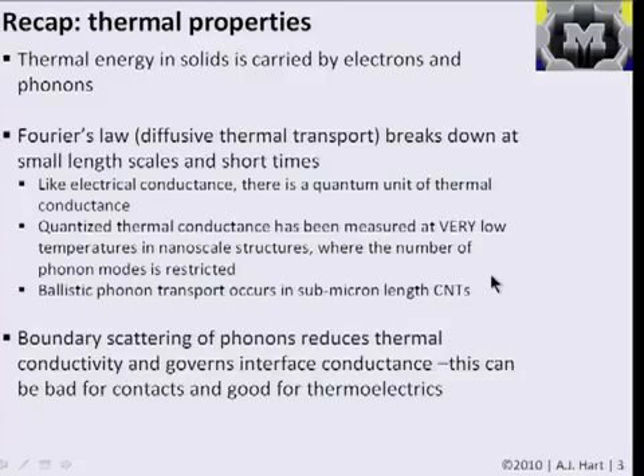And we also saw experimentally that in carbon nanotubes of submicron lengths, very short lengths, we see the same thing as we did for electron transport, that we see ballistic phonon transport, meaning that a vibration can go through without being interrupted. And that means that the thermal conductivity of the structure actually scales with length, which is something you would never see at a macroscale dimension. Of course, the amount of heat that's transferred would depend on length. The thermal resistance would depend on length of a bar of material if we had it. But the intrinsic property of the thermal conductivity wouldn't change. But this happens at very small scales.